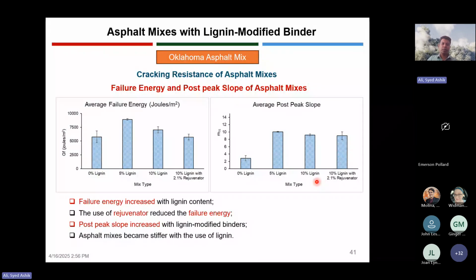Also, we wanted to look at the failure energy and the post-peak slope of the asphalt mixes. The failure energy we have found to increase with the lignin content, and the post-peak slope also increased with the lignin content. As I was mentioning, the post-peak slope is getting steeper. So as a result, it may be a stiffer and more brittle mix with the addition of lignin.